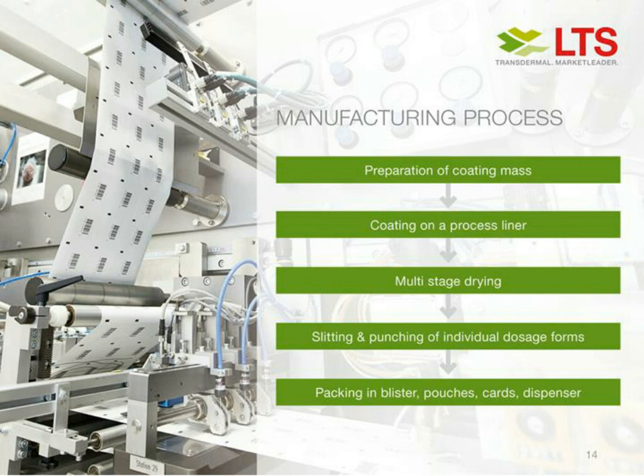And then this is being coated on a process liner. And then this goes through a huge drying tunnel at variable speed and varying drying conditions to actually maximize the removal of water or solvents used in the mixture. And subsequently, the master roll coming out from the drying oven is conditioned, and then it is slit and punched into individual forms, and in most instances is packed in blisters and in aluminium pouches. And by far, the aluminium pouch is really the packaging material of choice.